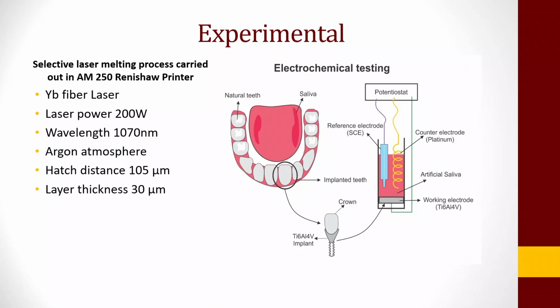So we have selected titanium, aluminum, vanadium, and we have printed this one using an AM250 Renishaw printer. We have used a laser power of 200 watts, and obviously using the argon atmosphere. We have a hatch distance of 105 microns and a layer thickness of 30 microns. And in this diagram, it kind of tells you that here is the implant, and we have used a potentiostat to run cyclic potentiodynamic and also the electrochemical impedance experiments.